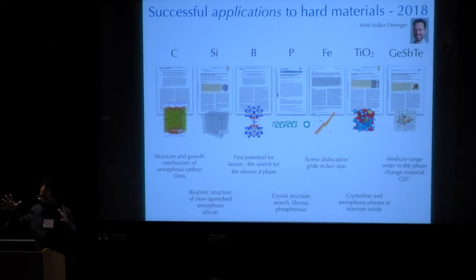We start quenching it. It's complete garbage, but we keep reevaluating small systems, 100-atom systems. We keep reevaluating the reference and keep improving the model until the quenches don't change. And I think 4 or 5 of these papers have that protocol in it. Now, that doesn't do everything. It doesn't do defects. It doesn't do surfaces. So it's not universal, but it's sort of on the way.